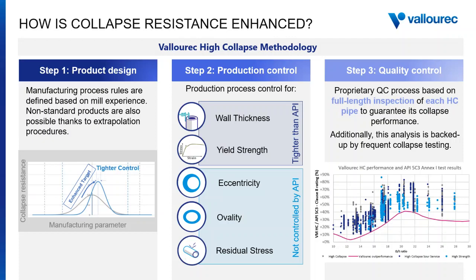And that is also the case for eccentricity, ovality, and residual stress, that are not controlled in API products, but for high collapse products, we control them. It's part of our process. So we do not only control in the quality control or the inspection section, but we also, during production, need to target more restricted and more challenging manufacturing rules or processes, as you would like to call it, in order to actually achieve higher collapse ratings.